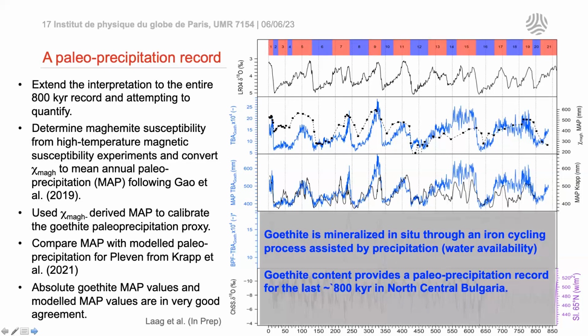So it seems that goethite at this site is being mineralized in situ through an iron cycling process that is assisted by water availability, precipitation, and that the goethite content provides for this site a paleoprecipitation record for the last 800,000 years for north central Bulgaria. So this was a very nice result and an example of iron cycling in loess that is not periglacially deformed.